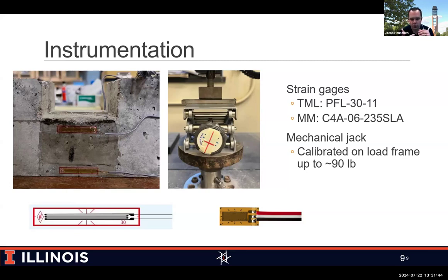For the most part, we use the larger gauges. These are our 30 millimeter gauge length strain gauges from TML. The longer length really helps with getting more of an average strain reading over that distance, especially since we were using standard large coarse aggregate. Then if we get a coarse aggregate near the surface, we don't get some weird readings. Although we did use some basically 1/4-inch strain gauges, which are more of what you would expect to be a standard strain gauge. We use those in addition to the longer gauges, just to help provide a little bit more confidence in our measurements.